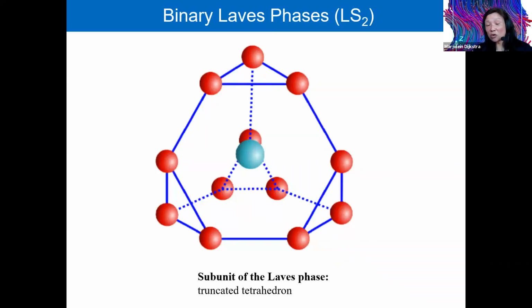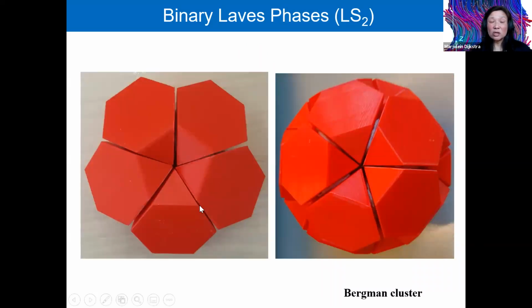These Laves phases consist of big spheres and small spheres. The big sphere is in the middle of a truncated tetrahedron, so that's why I discussed the truncated tetrahedron before. The small spheres are at the vertices of this truncated tetrahedron. There are 12 of them surrounding this big sphere in the middle. One can easily make five-fold symmetry using these truncated tetrahedra. If we use 20 of them, we can make an icosahedral cluster, which is also called the Bergman cluster.